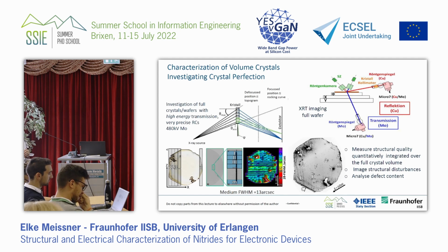So how do we characterize the volume crystal? This is what we do first of all. So we have a crystal which is grown, we take it out of the machine. This is an example for aluminum nitride crystal. And aluminum nitride we have quite a lot of chances to analyze, but you can imagine that it's not so easy if you have a big crystal.